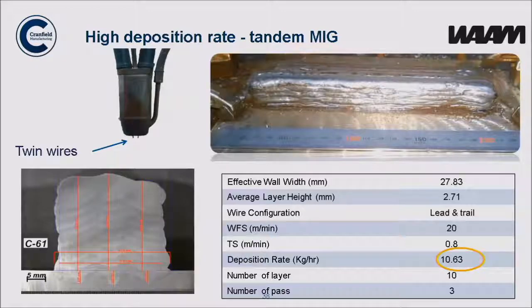So just looking at the first challenges about doing high deposition rate. You can do high deposition rate relatively easily. So this is using a tandem torch with 2 wires feeding into the same weld pool. And in this case, we achieved 10 kilos an hour. And in fact, we've been up to 15 kilos an hour with no defects. As long as you've got big parts, there's not really an issue in doing this. But as you can see, it's pretty rough and doesn't come out at a very nice shape.